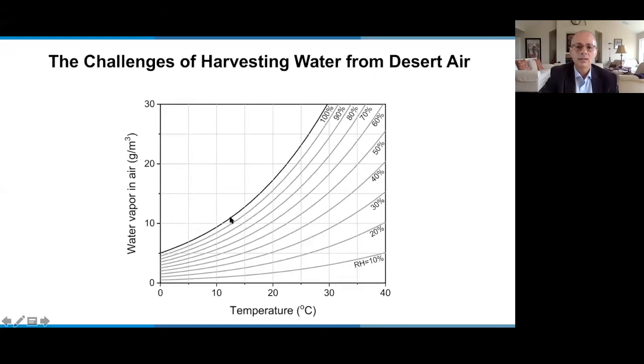If you're here, you have liquid water, okay? So here are two colors indicating the arid region, which is this pink, and the green is sort of, let's call it, the more watered regions of the world. But let's say that I'm in a city over here. I'm at 20% relative humidity and 30 degrees C. I have very little water in the air, okay? I have only 5 grams of water per cubic meter.